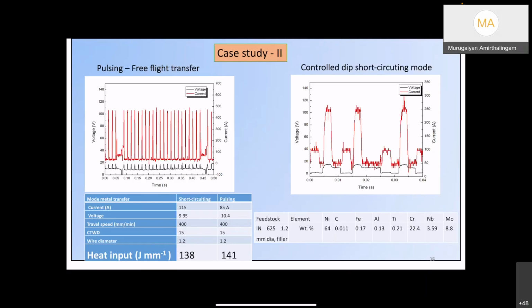Again, what do we do? We can manipulate the current voltage waveforms and the metal transfer behavior so that we can get a good columnar microstructure. So again, we can go back to the drawing board, understand what waveforms can give us a shallow temperature gradient or steeper temperature gradient, and then we can arrive at the optimal current voltage waveforms. And then we can understand how the waveforms can influence the arc energy, and subsequently how we can achieve the microstructure that we want.